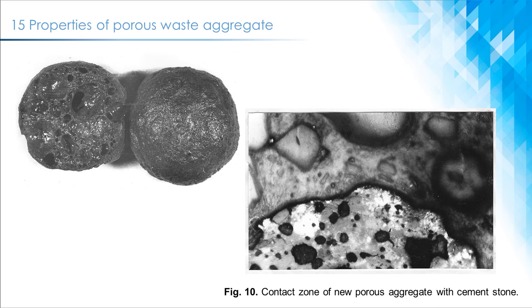A cement stone's contact zone with a large porous aggregate, figure 10, has the form of a winding line exactly repeating the granule relief, providing a tight and robust contact. The micro-hardness measurement method was used to study the micro-strength properties of the contact zone. The results have shown that the micro-hardness of the aggregate, 9,000-11,000 MPa, exceeds the micro-hardness of the cement stone in the contact zone, 4,000-6,000 MPa, and the micro-hardness of the contact zone is higher than that of the cement stone in the intergranular space, 1,500-2,000 MPa.